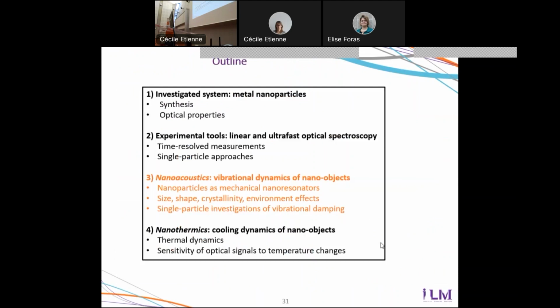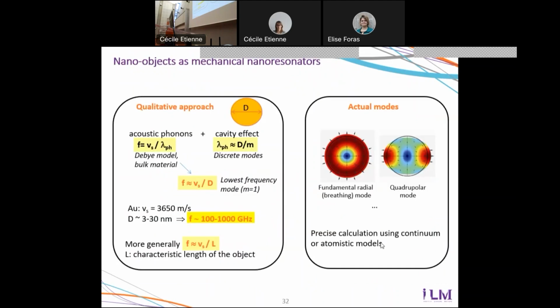I'm coming now to the part devoted to the vibrations of nano-objects. Just as a start, to realize that we are dealing with very high vibrational frequencies. Here you have an estimation of the frequencies of vibrational modes. It's done just by saying that phonons in infinite materials have a frequency which is the sound velocity divided by the wavelength. And if you have localized modes in nanoparticles, you have a cavity effect,